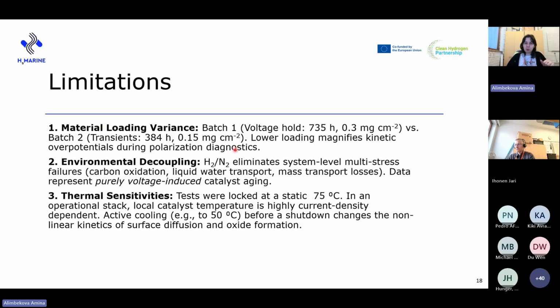For the second batch, we used lower loading, which will magnify the kinetic overpotential during the polarization curves — meaning the lower initial platinum loading will reduce the kinetic capacity of the catalyst layer. So the equivalent loss of electrochemical surface area will probably trigger higher voltage overpotentials during the polarization curves.